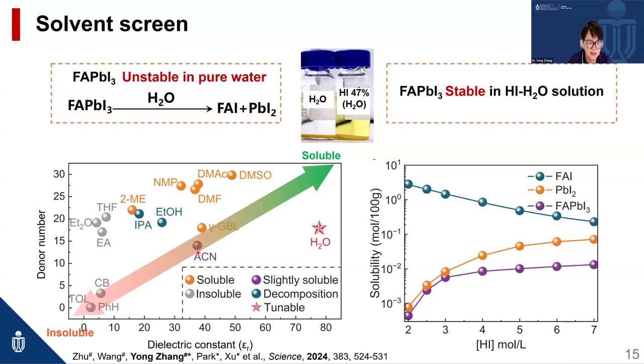We found that our previously used acetonitrile is in the center position relative to water. So if we can change water's dielectric constant, then we may stabilize it. This is the reason for stabilizing FAPbI3, and the synthesis is possible.